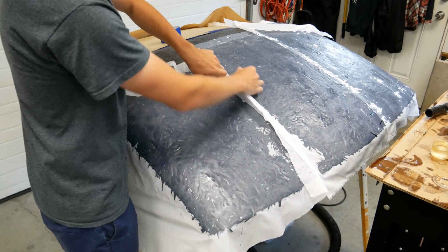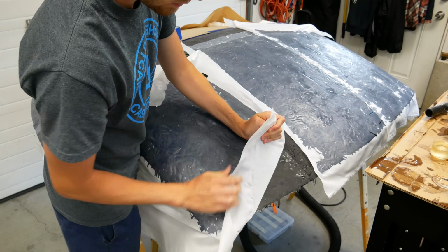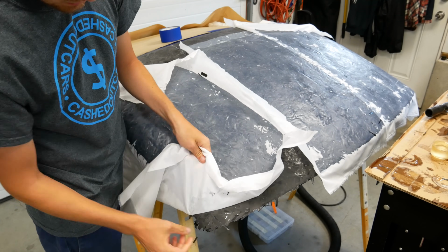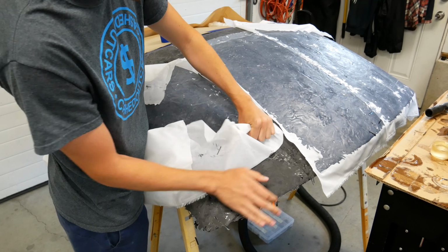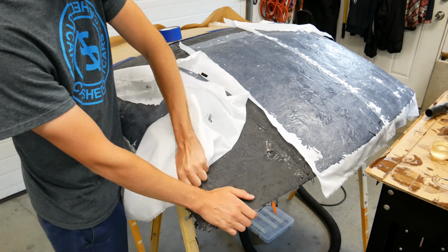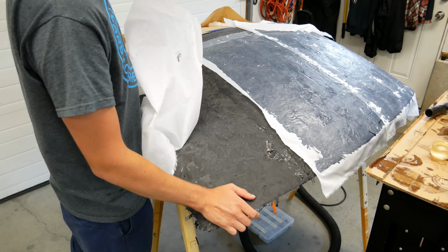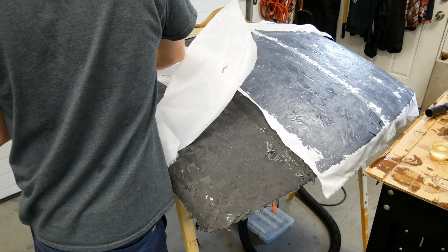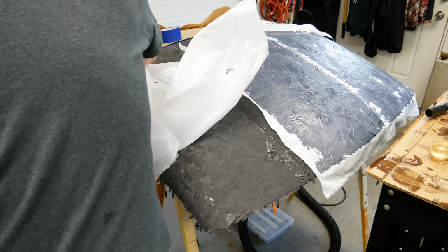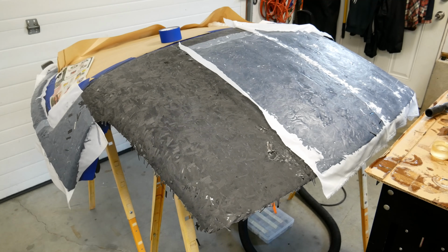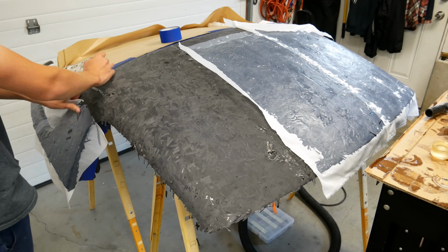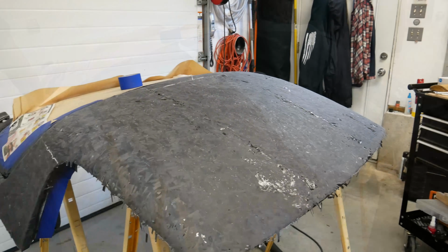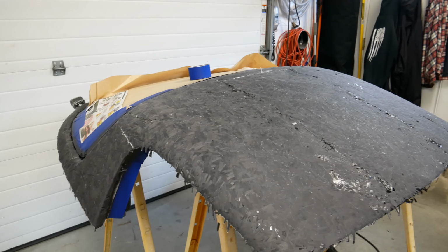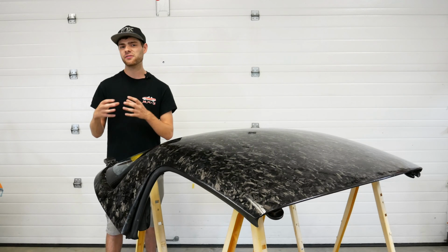The first thing to do after the resin was cured was remove that peel ply fabric. To do this, you simply lift up an edge and carefully pull it back. You'll see the nice uniform texture that it reveals underneath. Unfortunately, with this part, as you could see, there were a few areas that didn't quite get enough resin, and the carbon was left a little bit dry and the texture wasn't quite so uniform. We're going to go ahead and fix that.